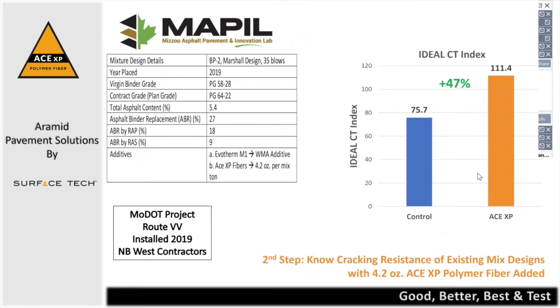Another job we did over in Missouri. Again, plant mix. And there you can see the stats of the asphalt design on the screen. The virgin binder grade was a 5828. The contract grade was 6422 with adding the RAP and the RAS in. And you can see the total asphalt content was about 5.4. Now, in the scheme of things, 75.7 for the control isn't bad, but look where we took it, 111.4. Again, that's with a single dose of ACE XP, about a 47% increase.